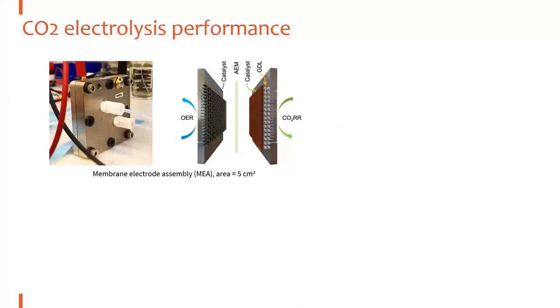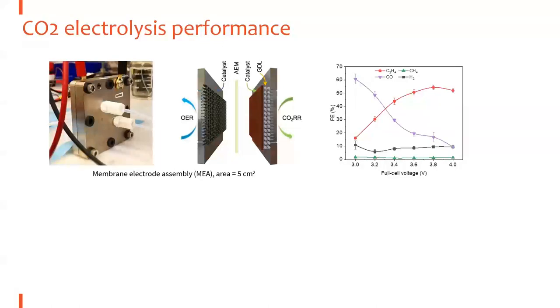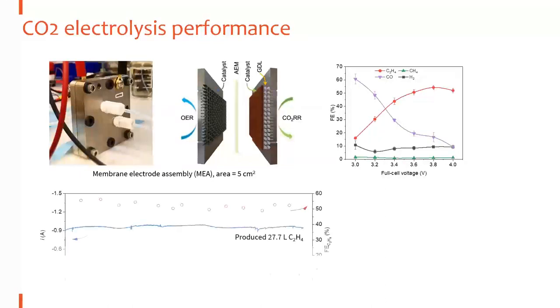So how can we upscale the reaction? Now we are developing our MEA device, the membrane electrode assembly device, which is the most promising device. It has already been commercialized in fuel cells, and is also under commercialization for water electrolyzers. So we borrow such concepts of MEA into our CO2 electrolysis, and we can work on a larger area of 5 cm². Of course, we are trying to further work on 25 and 100 cm² MEA devices. But here we showcase the results from 5 cm², and we found that the selectivity remains the same and the voltage is not bad.